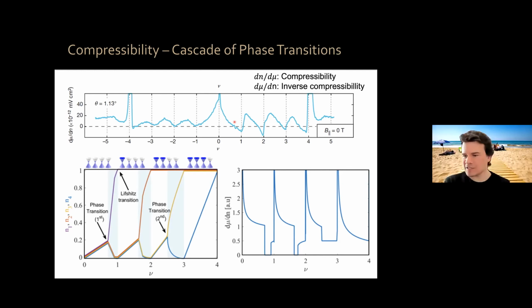Now, the description of this is a little bit complicated. The only message that I want you to walk away with is the fact that something happens near each integer, and that something that is happening, to 0th order, can be understood as the following. When you are at charge neutrality, you have these 4 Dirac cones, these 4 flavors that you want to fill: spin up, spin down, valley K, valley K prime, in the simplest case. As you add charge to your system from charge neutrality, all of these 4 flavors start to get filled at the same time. However, near an integer, when you have put about 1/4 of an electron per moiré unit cell in each of these flavors, so a total of 1, the system decides to spontaneously flavor polarize, sends all the charge carriers to occupy 1 flavor and empties the other 3. And then you start again.